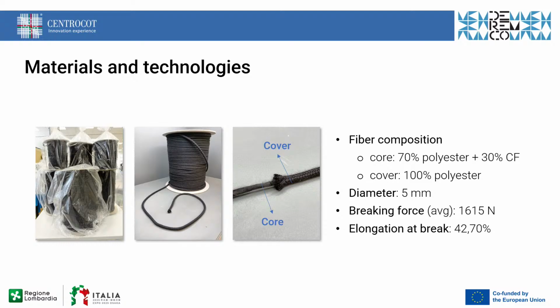Here you can see some products realized, and since we are a technological testing center, we also characterize this material. And the analysis demonstrated that the core of this rope is made from 70% polyester that we know to be recycled because we keep the traceability of the materials along all the recycling process. And 30% of carbon fiber, while, as I previously said, the cover is just made from polyester because of practical applications. The diameter of this rope is about 5 millimeters,